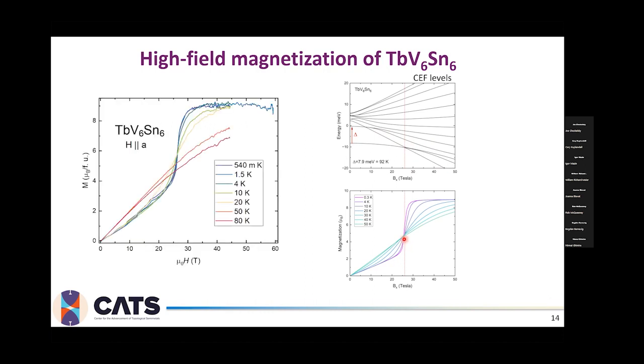So what we did, it again turns out that the theory works pretty well in terms of defining the transition at around 27 Tesla. There is some discrepancy, like I see 3 very small transitions at 8, 12, and 17 Tesla before that huge metamagnetic transition at 27 Tesla. We also noticed that the slope of M versus H is much steeper in our experimental data than it looks in the theoretical prediction.